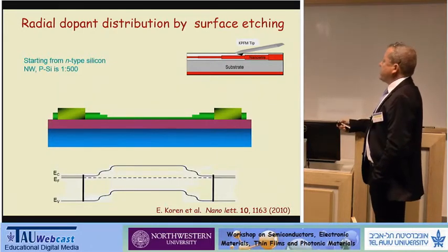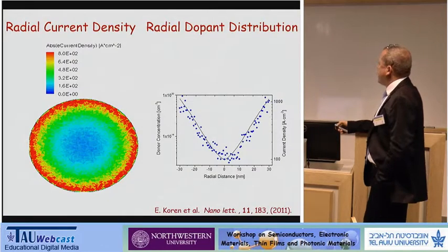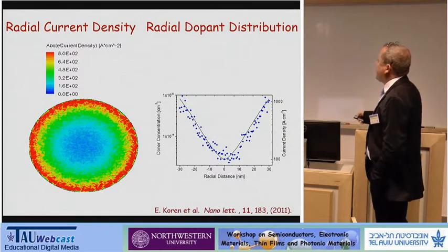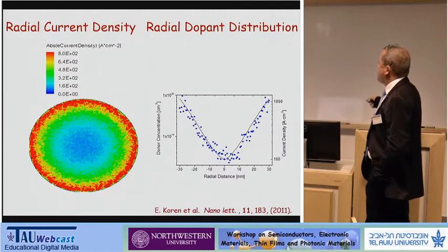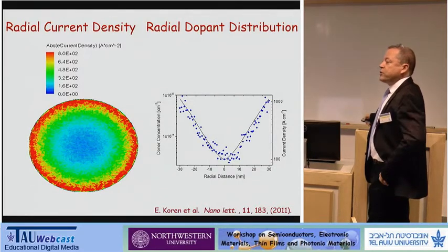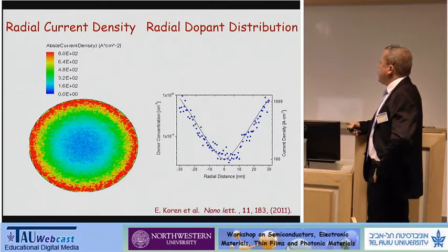We did a lot of simulations and a lot of measurements. I'll just show you the end result. The end result is that we end up with a very highly inhomogeneous distribution of dopants like this. So you see that going 30 nanometers into the nanowire, this is the middle of the nanowire, the dopant distribution decreases by almost 2 orders of magnitude.